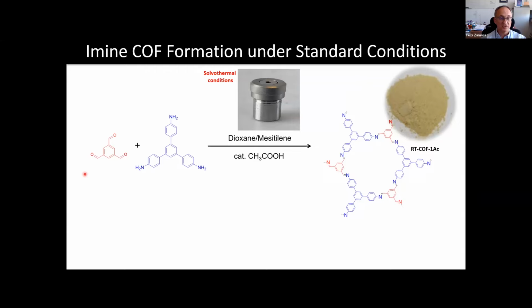Okay, you combine two building blocks, for instance this simple trialdehyde with this simple triamine, and then you typically have to use solvothermal conditions. This is the most typical solvent mixture that we use, dioxane and mesitylene, and you have to use a catalyst, for instance acetic acid. If you do that, at the end of the day, you form this imine-based COF. But if you isolate the material that you produce during this reaction, you will end up with a kind of powder, like the one that we have in this picture.